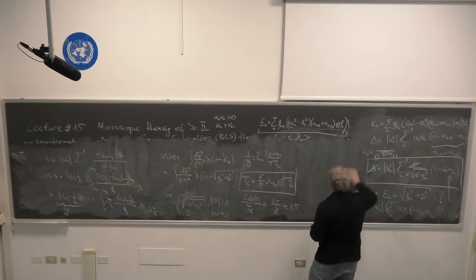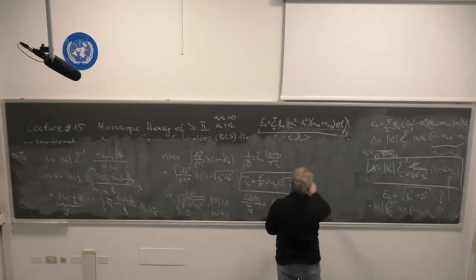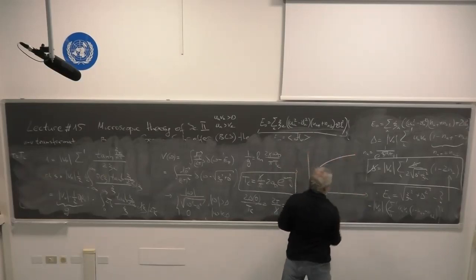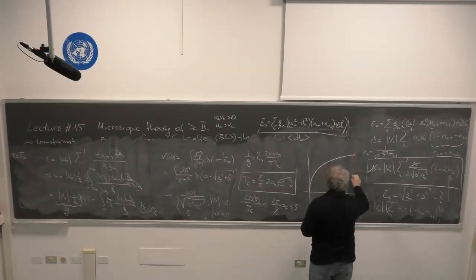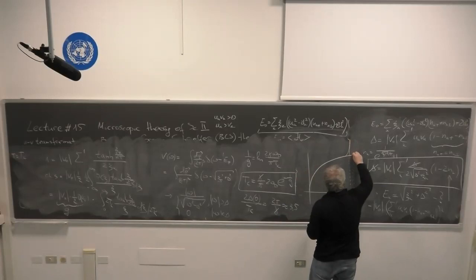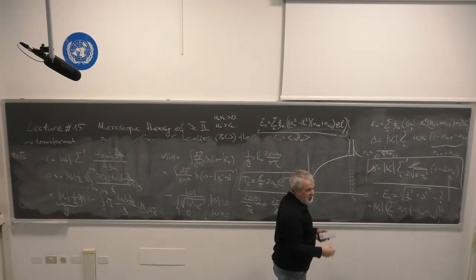However, I would like to remind you, whatever I'm saying about the density of states, we have 3 variables. The density of states behaves as a square root. The critical temperature or delta or whatever is of the order of a few kelvins. Even if it is room temperature, it is small compared to the Fermi energy. So we are affecting the density of states in a very narrow region, because delta is much smaller compared to the Fermi energy.